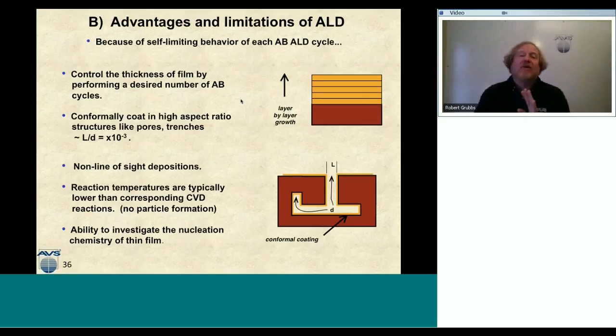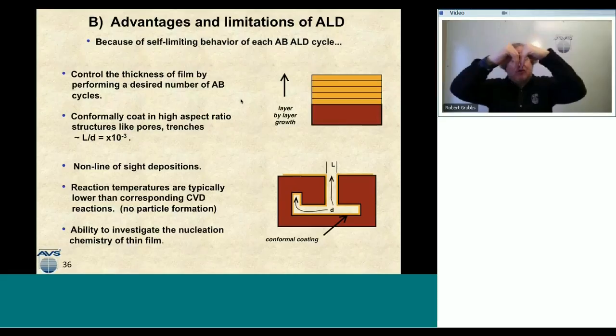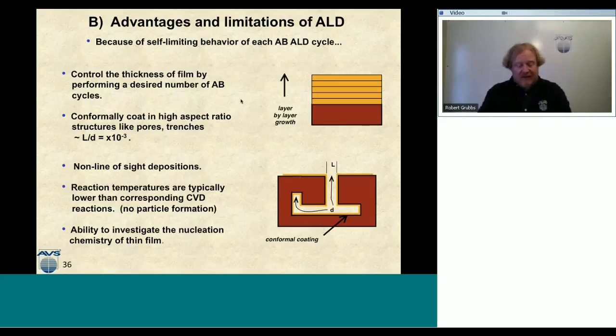I mean, it's absolutely remarkable compared to the other deposition techniques that I've covered, that you can have this really acute control of thickness. The next, probably as equally if not more important advantage of ALD is that it can conformally coat these high aspect ratio structures. So no other technique can get into a very small trench and put down the same thickness of material from the top to the bottom. I mean, it's a remarkable technique. If you're in the stone age of CVD or sputtering, this is just like a brand new day.